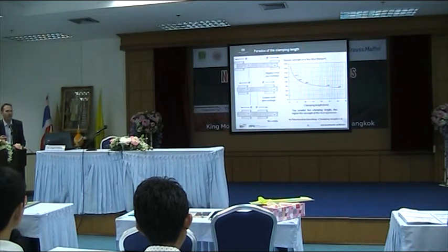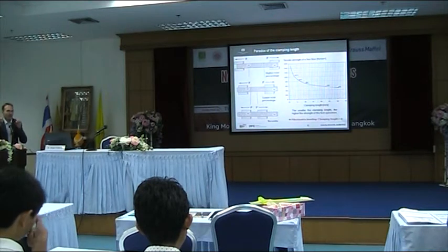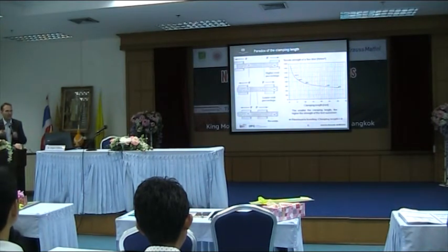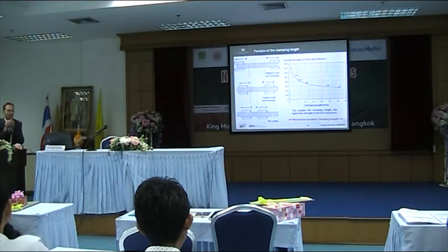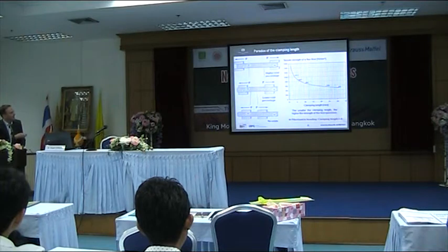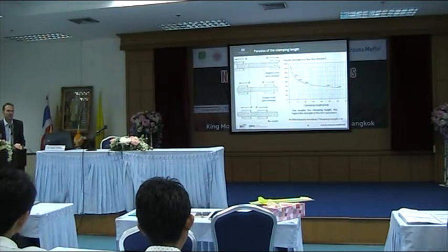Now, imagine in a part you have not a clamping of the fibers, but the embedding of the fibers in the matrix. And so normally you can say if a fiber is totally impregnated, so fully surrounded with a matrix, you would have a clamping length going to zero because you have no free length of the fiber. If the matrix completely surrounds the fiber, we have a really good embedding, so that means the free length between the clamping of the fiber would be nearly zero. So why I'm saying this is something which gives a hint to impregnate the fibers as well as possible.